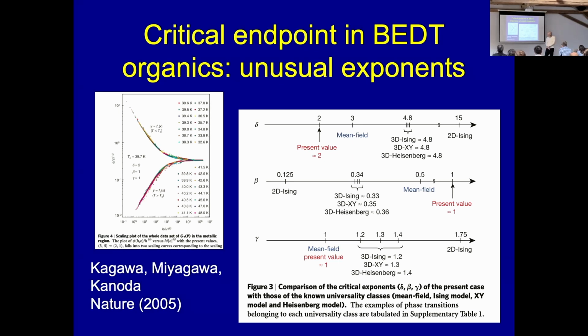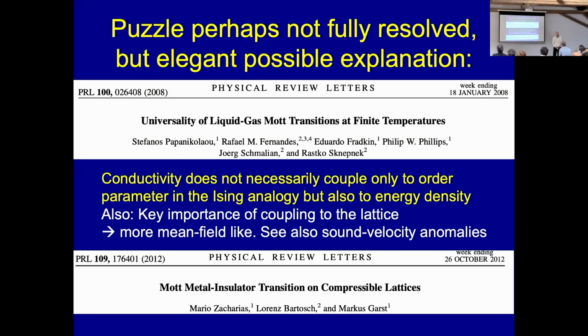And especially for delta, the thing which is really surprising is that not only do they not really fit the Ising model, but they are also very different from any known delta exponents from any known transition. Delta equal 2 is extremely surprising, as you see from comparison to these well-known StatMech models. So this was a subject of long debates, and perhaps this is the first thing we encounter in this talk which is perhaps not fully resolved at this stage. This puzzle has received a few explanations. So a few explanations means probably a few too many.